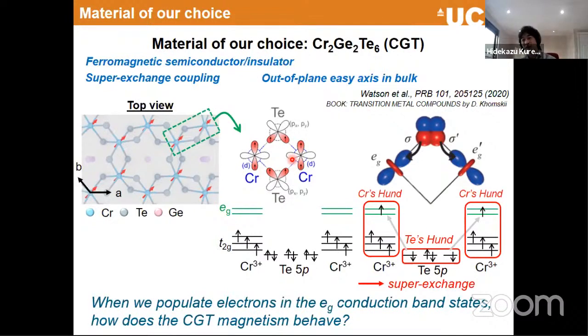I agree. That was always the point of discussion, whether, for example, when you dope one electron in this EG conduction band, I think the Fermi level is within this band. That means that the electron is fully delocalized, and then this metallic effect can produce the ferromagnetism. We can understand that microscopically from the calculations. I don't see why not.